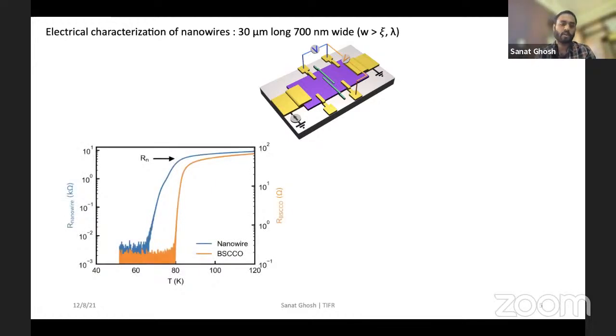So first we do this 4-probe measurement of resistance versus temperature. Now you see two scales here. The left scale shows the resistance versus temperature of the nanowire, and the right scale shows the resistance versus temperature of the BISCO. Now the blue curve that is shown here has two parts. If you see the electrode geometry, you can clearly see that this involves the superconducting nanowire plus some part of the extended flake. And we get the pure nanowire response once the extended flake has gone superconducting. Then whatever response you see is coming from the superconducting nanowire, and we define the nanowire normal state resistance at the temperature where the bulk part has gone superconducting.